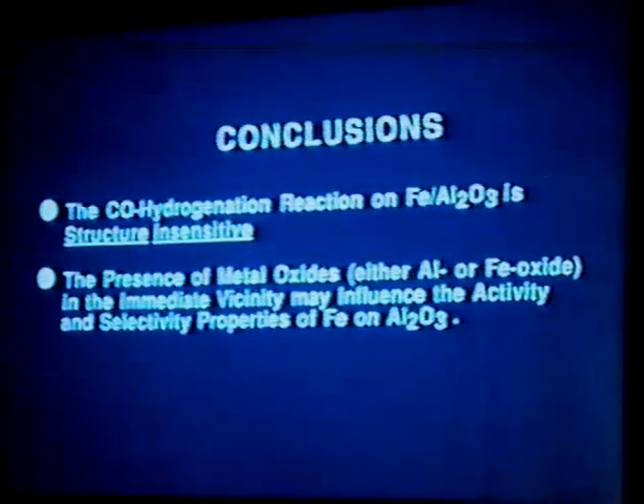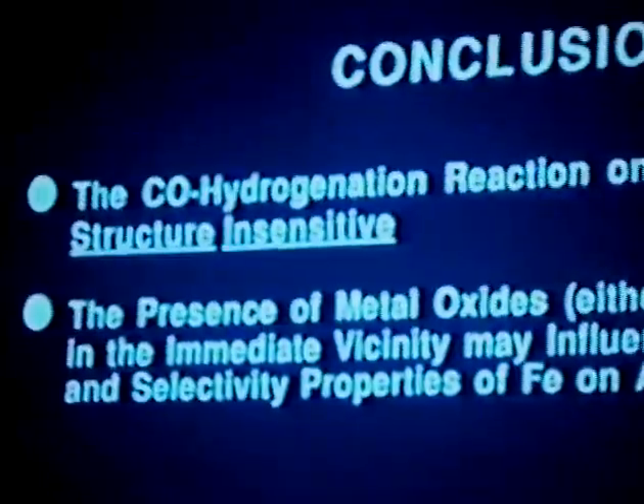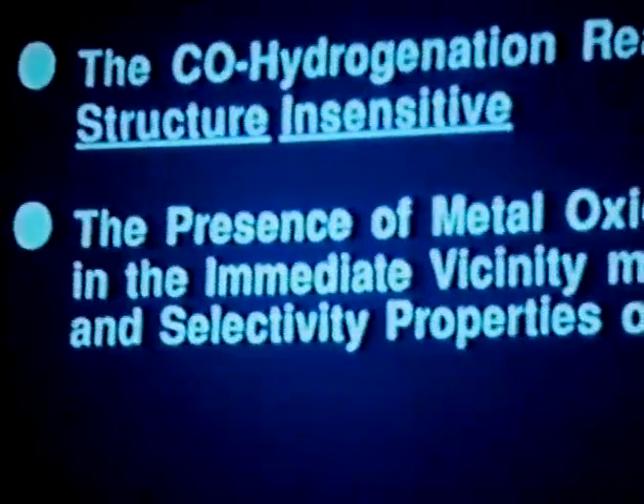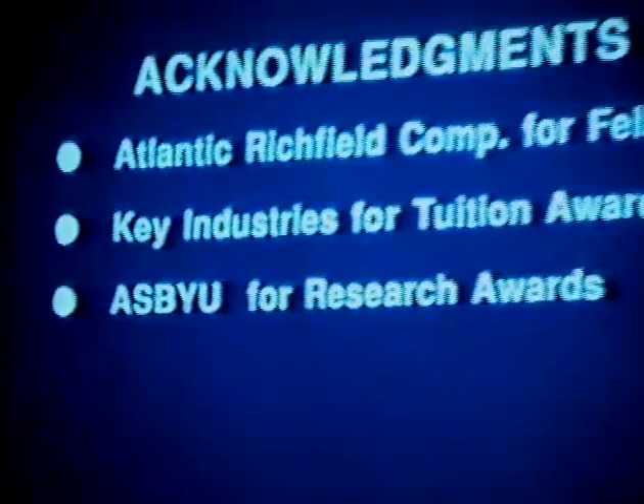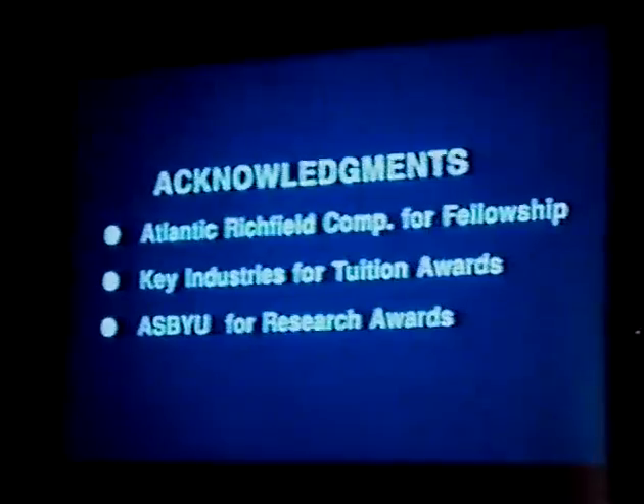From these we could come to the following conclusion, that CO hydrogenation reaction on iron alumina is probably structure insensitive. And the presence of metal oxides, either in the form of alumina or unreduced metal oxides such as iron oxide, in the immediate vicinity may influence the activity and selectivity properties of iron alumina to a greater extent than the structure itself. I would like to acknowledge the following for financial support.